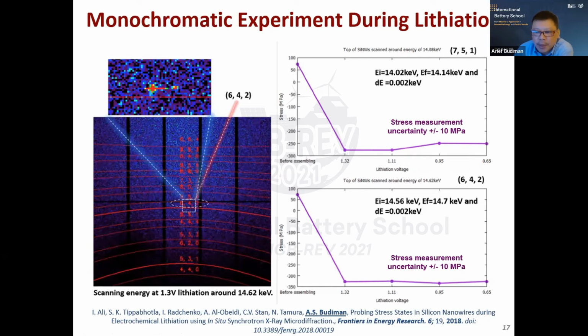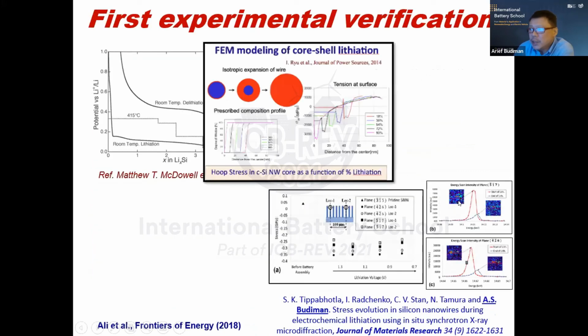I hope for those who are material scientists, you still remember this is probably engineering materials 101, right? Failure of materials, cracks, happens only in a tensile stress state, not in compressive. So this compressive stress state is observed for the first time by our technique. And it's only possible with real in situ electrochemical lithiation. So this is a proof that we have a lot of knobs to adjust if we have nanostructures, that is nanowires in this case. So this is in terms of the performance.